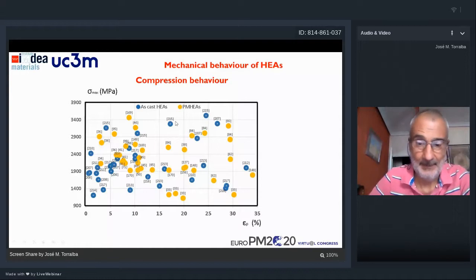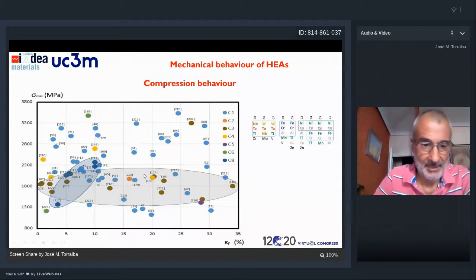And we have seen that we have this distribution quite similar if we consider more or less the same amount of papers published with the same materials. So you can see that we can find some materials with a high level of compression strength and a low level of deformation, and even some materials, both from ingot metallurgy and from powder metallurgy, with a high level of compression strength and a high level of deformation. If we go a little bit further and we analyze the compositions, here we have most of the transition